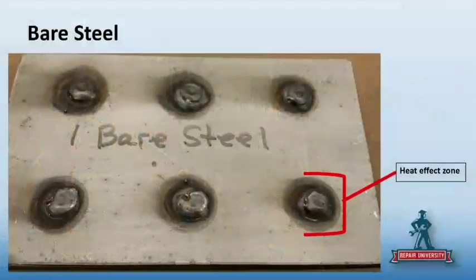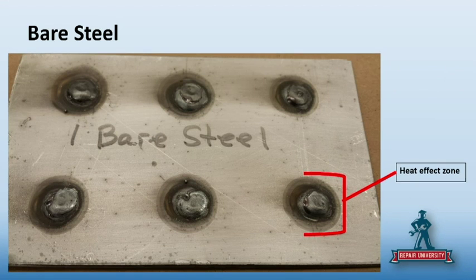And then let's go through it. Some great examples here, Shawn. So yeah, it's the same thing here. So this is just showing the front side of completed welds with coatings. So this was bare steel, so you can see the heat effect zone around that weld nugget is very small. So that's a really good weld. You can see consistent halos around each weld.